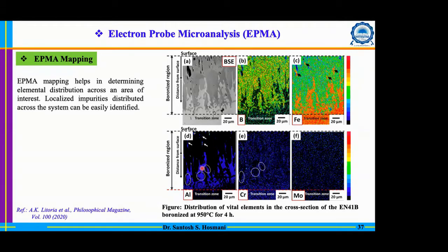However, in the matrix, you can clearly see a very high, blue colored region. That means we have the presence, or segregation, of aluminum in the surrounding matrix. But when you go to the transition zone and matrix, it again appears dark. That means the matrix region is depleted of aluminum. That is because it's a rejection by the boride, and the migration kinetics of aluminum is not great. Because of that, it remained there.